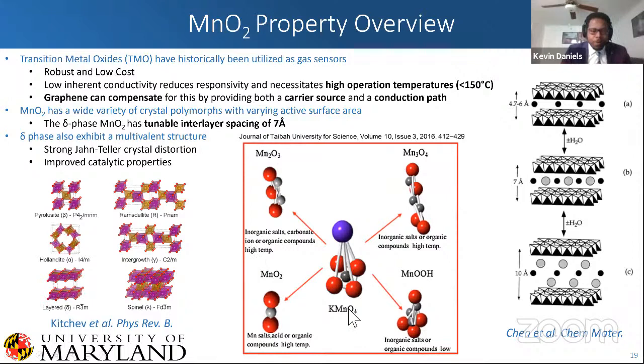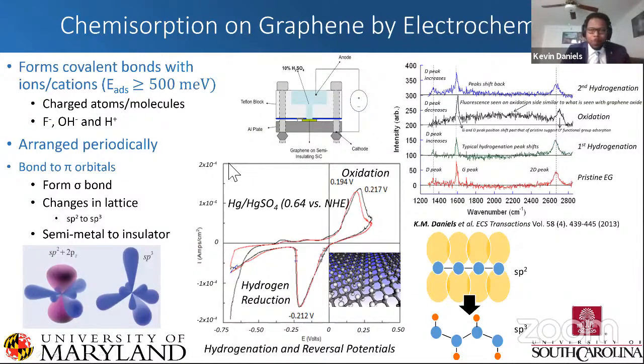As you can see here, if we were to use potassium permanganate, there's actually a lot of different compounds that you can get that's not manganese dioxide. But this material is very interesting because it has very large interlayer spacings in between the material that can be tuned by putting in different ions in the material. So it can be seen as a pretty good sensing material that we can tune to whatever molecule we're interested in sensing.